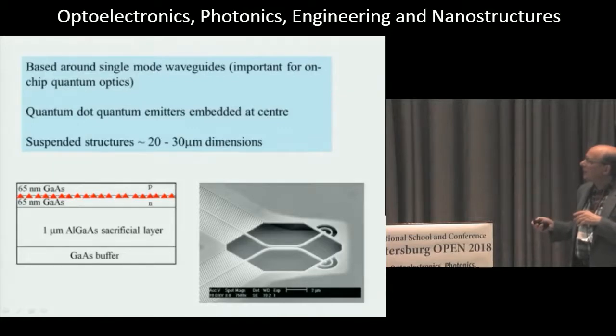And so this is the structure as it's grown on gallium arsenide with an aluminium gallium arsenide sacrificial layer, and then the waveguide region with quantum dots embedded at the center. So the quantum emitters are embedded at the center. And we remove the sacrificial layer by wet chemical etching and create suspended structures of the type you see here. So this is air above them on all sides of the directional coupler. This gives us very large refractive index contrast and very strong optical confinement. And typical sizes of the structures that we can easily make are 20 to 30 microns.